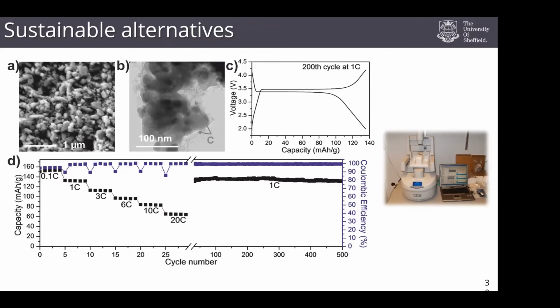And this C rate is telling you how fast we're charging and discharging that battery over an hour. So the higher this number, the faster you're charging and discharging over an hour. So 20 times over an hour, charging and discharging in a matter of minutes. And you're still getting very good capacities, even at those very high charge discharge rates. So even after 200 cycles, we're not seeing any depreciation in capacity.